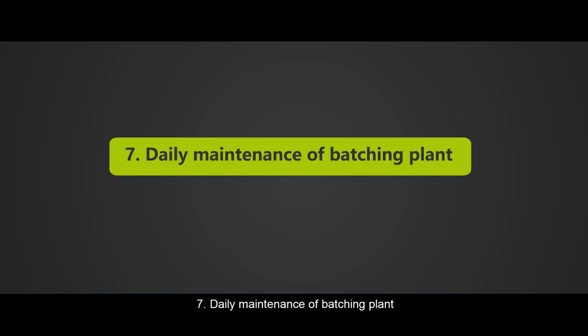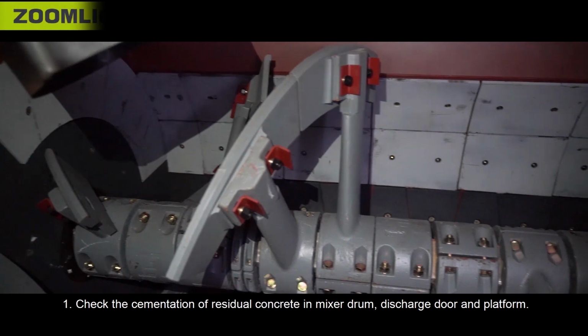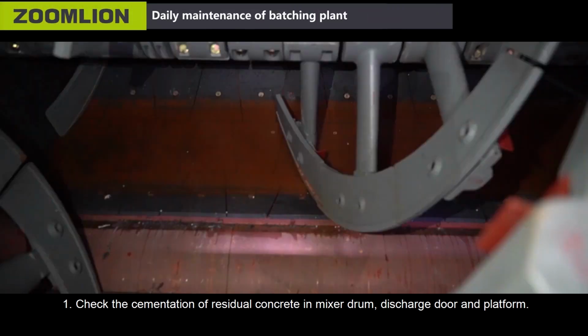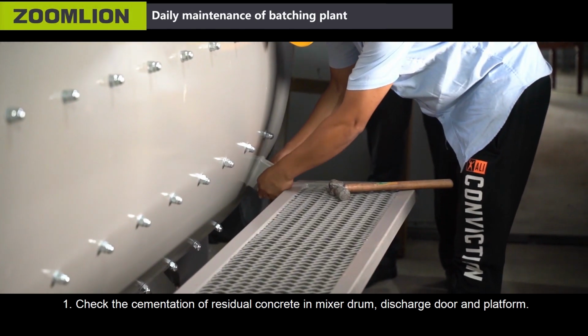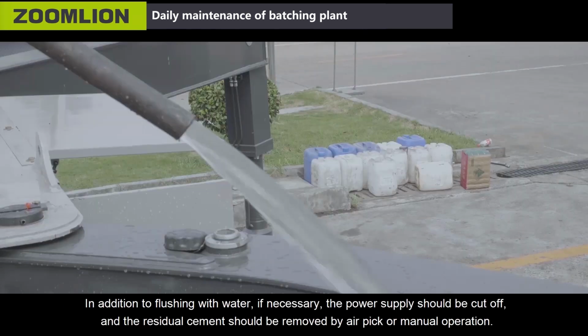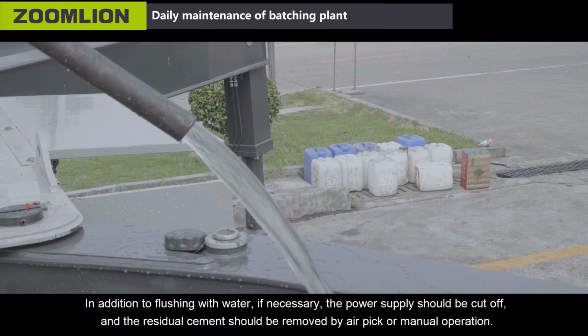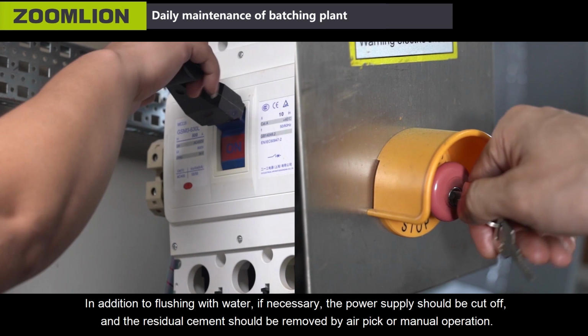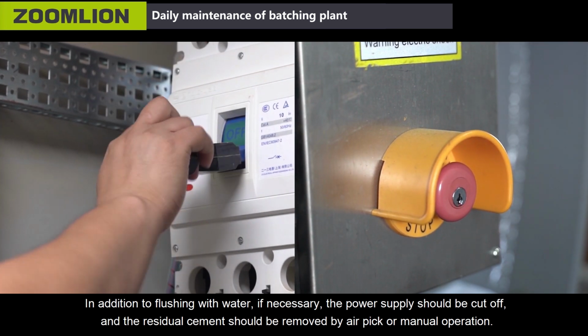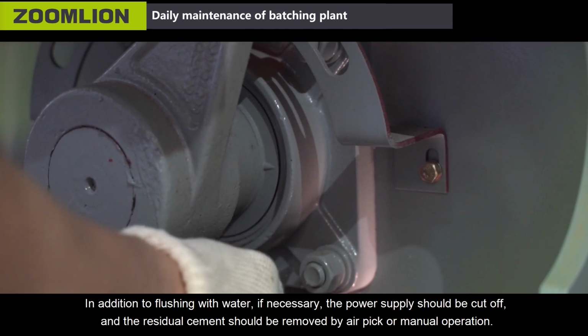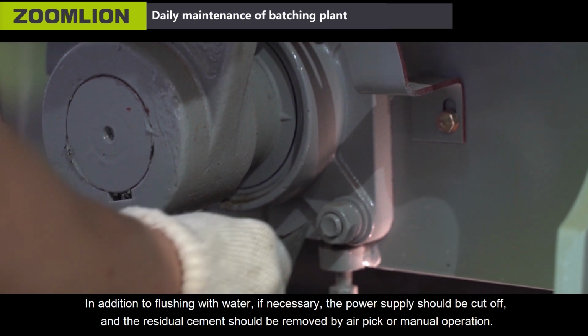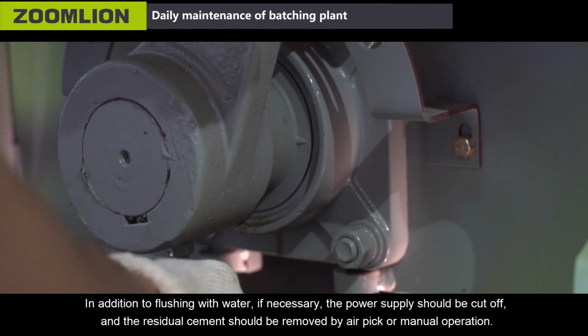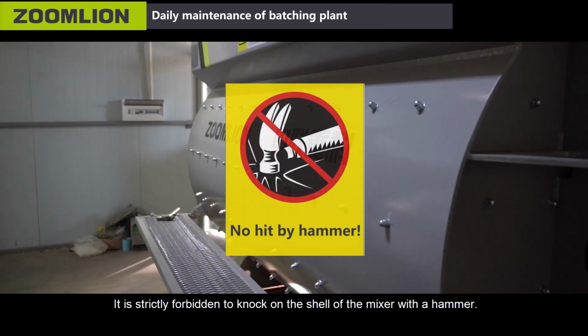7. Daily maintenance of batching plant. First, check the cementation of residue concrete in the mixer drum, discharge door and platform. In addition to flushing with water, if necessary, the power supply should be cut off and the residue cement should be removed by an air pick or manual operation. It's strictly forbidden to knock on the shell of the mixer with a hammer.